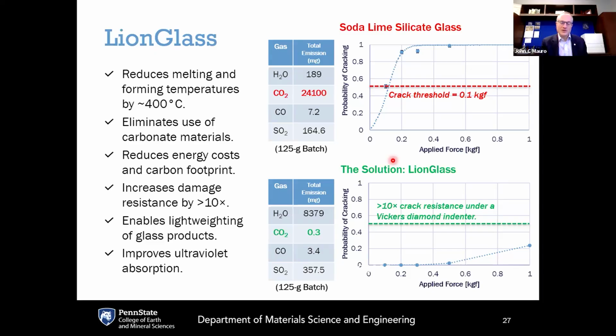Another cool thing is that the retained strength of the glass after damage is quite a bit higher. The upper right plot shows the probability of soda lime silicate glass cracking under a Vickers diamond indenter with increasing load. The crack initiation or crack threshold is the 50% crossover here, where you've got a 50-50 chance of popping in a crack. In soda lime, that happens at 0.1 kilogram force. For Lion Glass, you can see at 0.1 kilogram force there's a zero probability of cracking. And if you multiply that by 10, it's still just a 25% probability of cracking. So it has a much higher damage resistance.